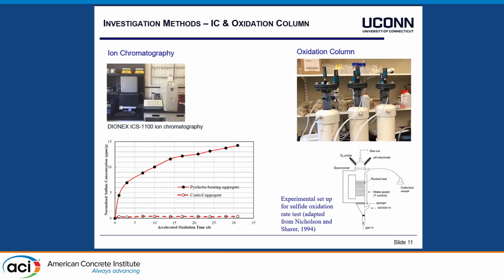Then an example of using ion chromatography is shown here, where, as I said, you expose the aggregate to an oxidizing agent. If you have a control aggregate, you don't see any release of sulfate ions, and so you also cannot measure them. But if you have a pyrrhotite-containing aggregate, especially with pyrrhotite available at the surface so that it can react, then you see an increase in sulfate ion release, and you could correlate this to the reactivity of this type of aggregate, or the exposed pyrrhotite from this aggregate.